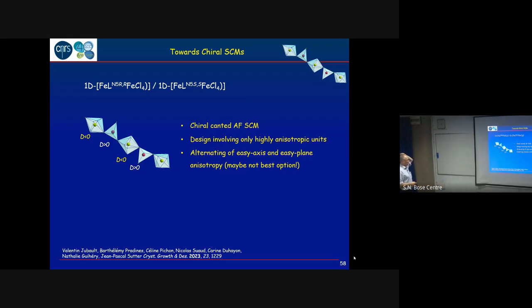So I don't remember where I stopped here. Yes, so now we have a way of playing with the anisotropy sites. Of course, here we have positive and negative, which is not the best situation. So what we are currently doing is trying to use a center that would give negative anisotropy, and then we expect to have better results.